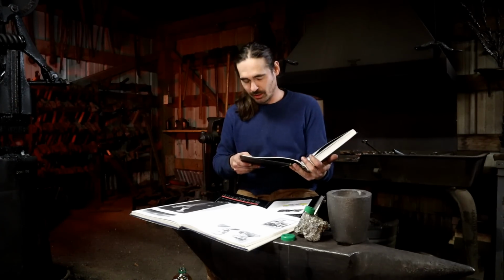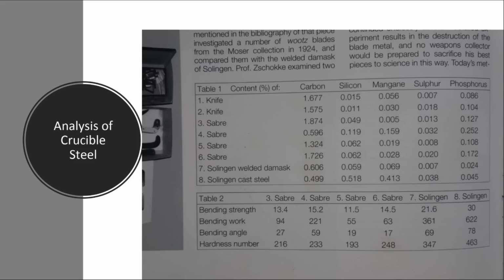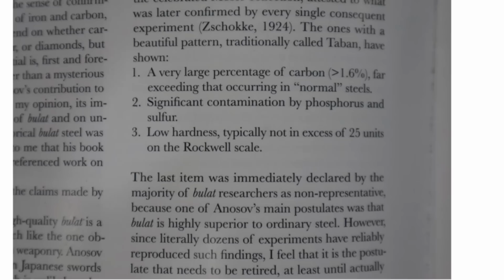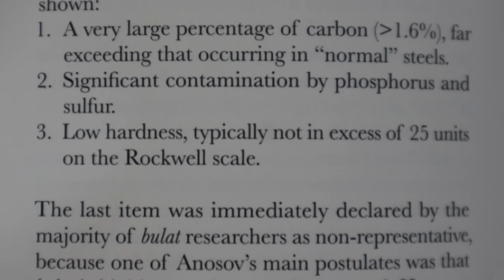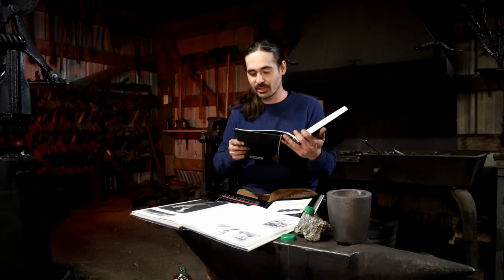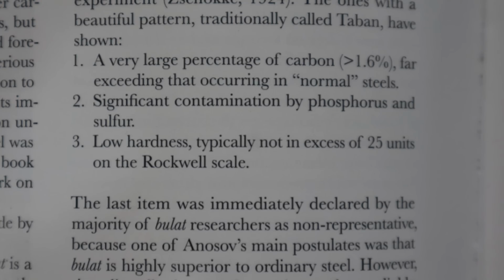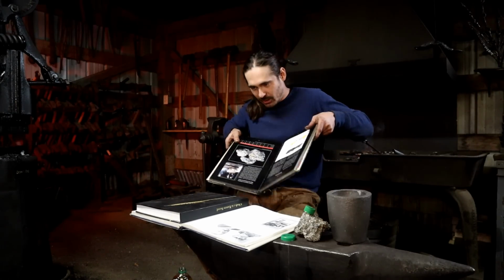So, a study of several Wootz blades concluded the following, that they have a very large percentage of carbon, >1.6%, far exceeding that of normal steels. Significant contamination by phosphorus and sulfur, and what's more important, a low hardness typically not exceeding 25 units on the Rockwell scale. 25 units on a Rockwell scale is approximately your mild steel. The fact that it is typical for a crucible steel sword from the Middle East to not exceed 25 to 30 units on the Rockwell scale means that they were not heat treated.